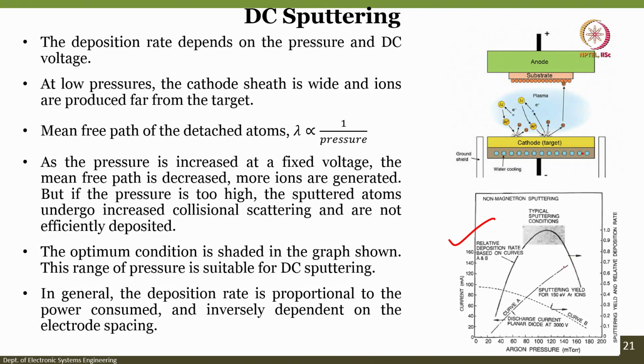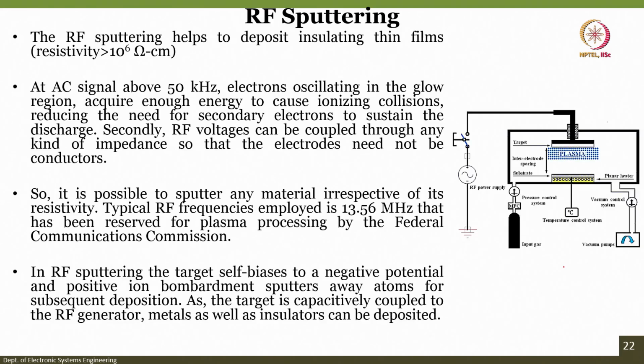In general, deposition rate is proportional to the power consumed and inversely dependent on the electrode spacing, right. So, if the electrode spacing is reduced, the deposition rate is higher. If the electrode spacing is increased, the deposition rate is lower. If the power is increased, the deposition rate is higher. If power is decreased, the deposition rate is lower. So, that is how the combinations are there.